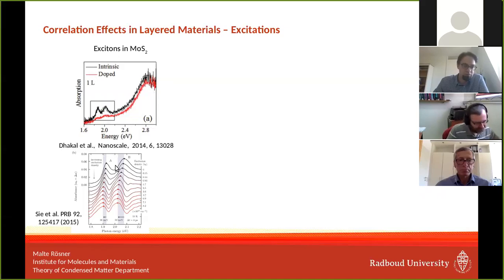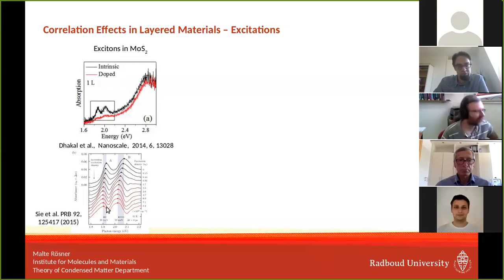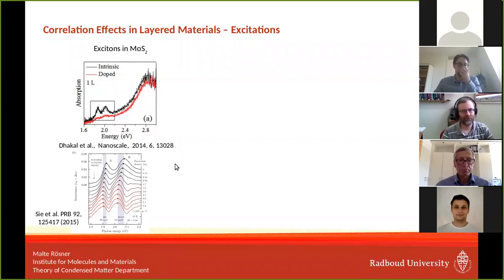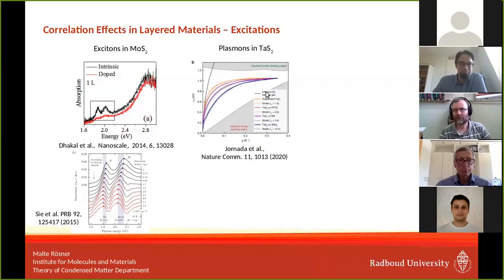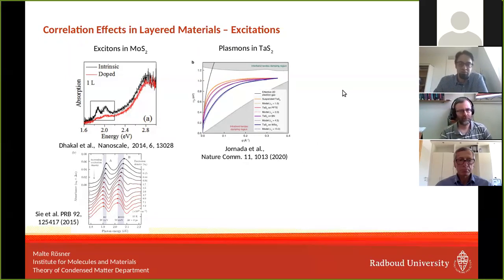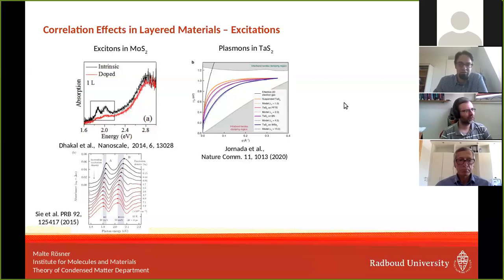These excitonic spectral features are again a function of the surroundings — here more a function of an outer probe, so this is an out-of-equilibrium state described in more detail later. Next to excitons, we also have plasmons in these metallic layered materials, which again behave differently than in 3D: instead of a constant plasmon dispersion, we have a square root-like plasmon dispersion for small momenta, which then flattens for larger momenta. As a function of the environment, these excitations can strongly change.